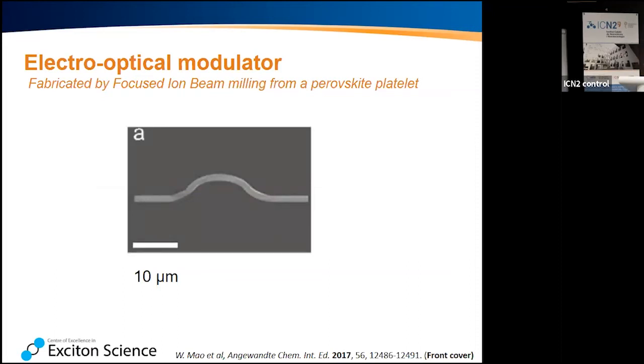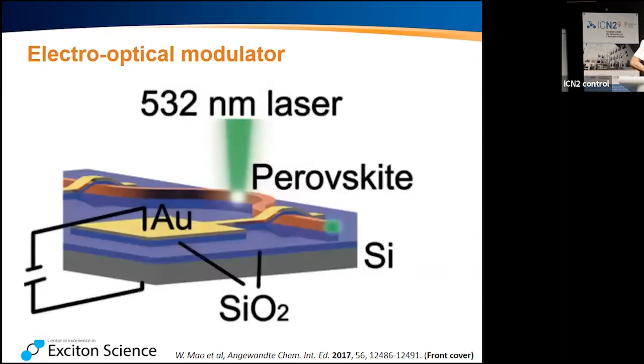Now imagine that you take this perovskite and you place it onto a silicon wafer that has a thin silicon oxide layer on top. And then you evaporate silicon oxide on the two sides and put again a gold electrode on top. Now you have your perovskite sandwiched between two insulators and two electrodes, and that allows you to apply an electric field to your perovskite. So that's shown here. You have your silicon wafer, which is quite strongly doped, so it is conducting, so we can use it as a conductive substrate, with a layer of silicon oxide on top. And so that's our bottom structure here. And then we put again silicon oxide on top and a gold bridge across. So here's the spot where our perovskite is sandwiched between two electrodes, but we can't have charge injection into the perovskite because there's silicon oxide on both sides. So it's really just an electric field that we can apply there.